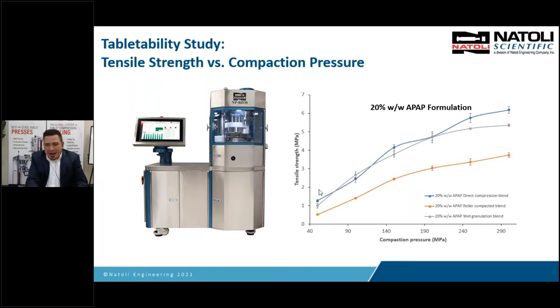And if you roller compact it, you need more pressure because we're losing some of that energy through the compaction process of the roller compactor, but it's still very reasonable. You're still about 130 megapascals of pressure, which is very normal for pharmaceutical.